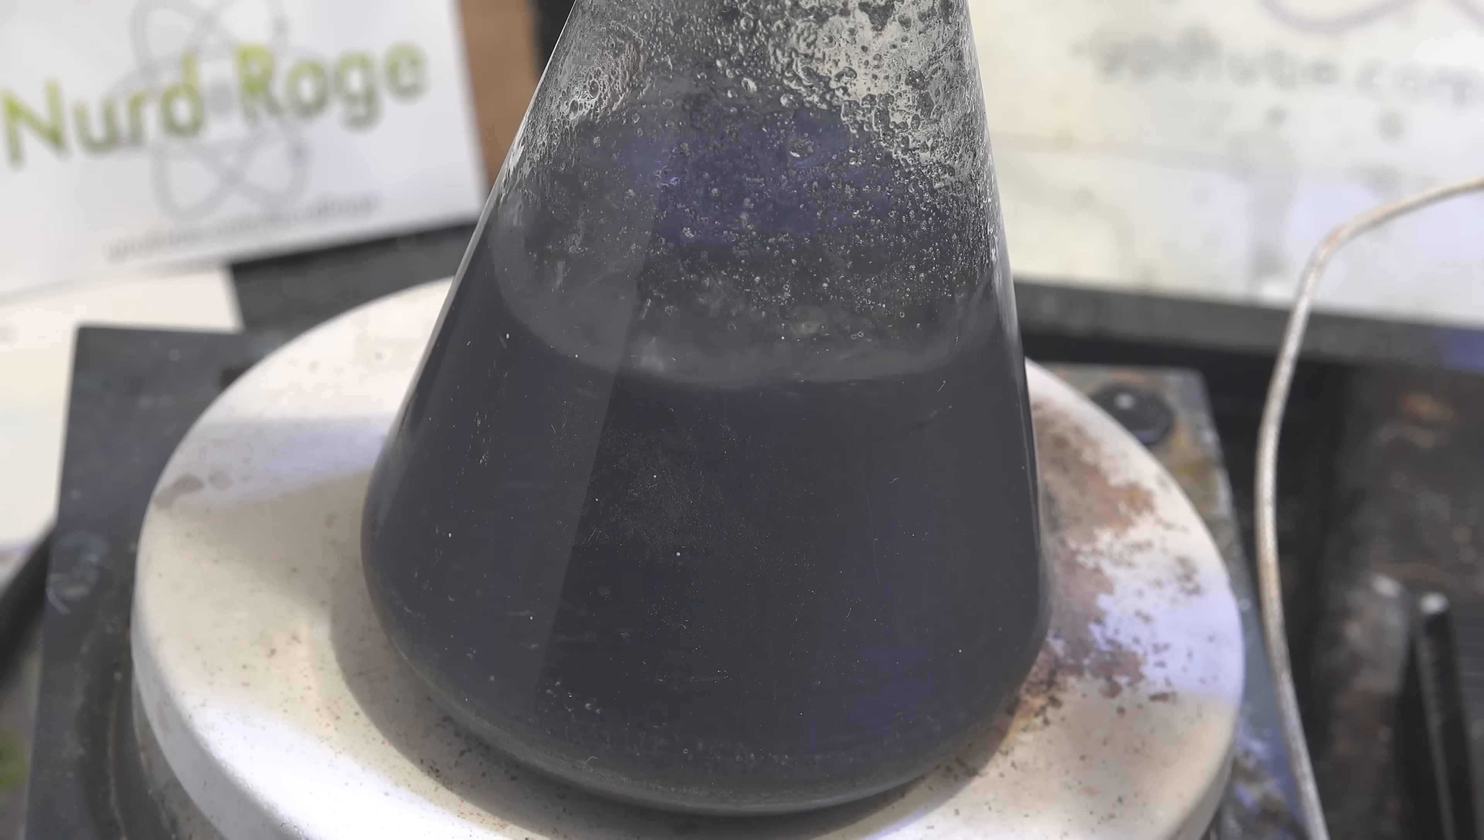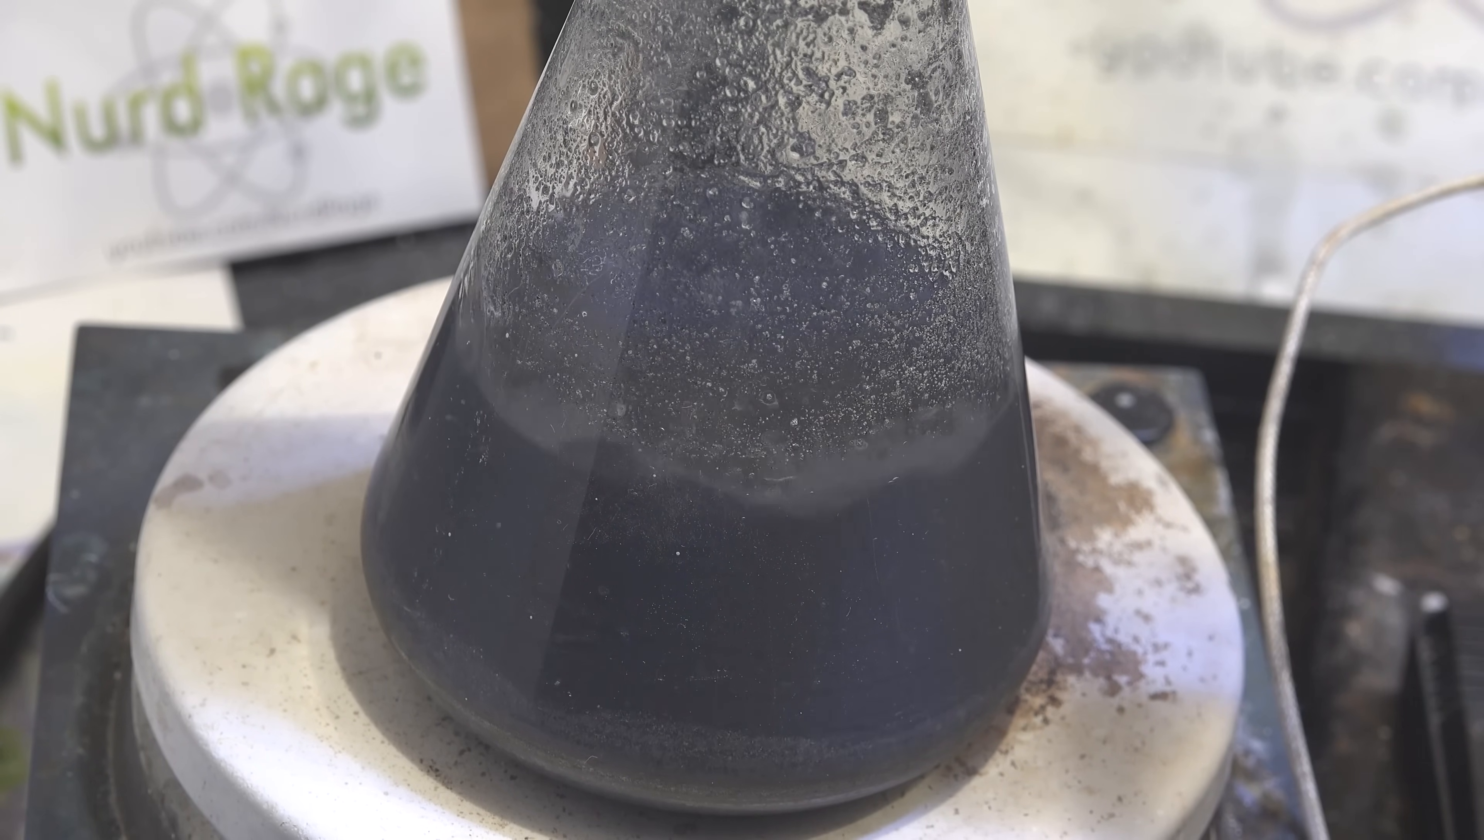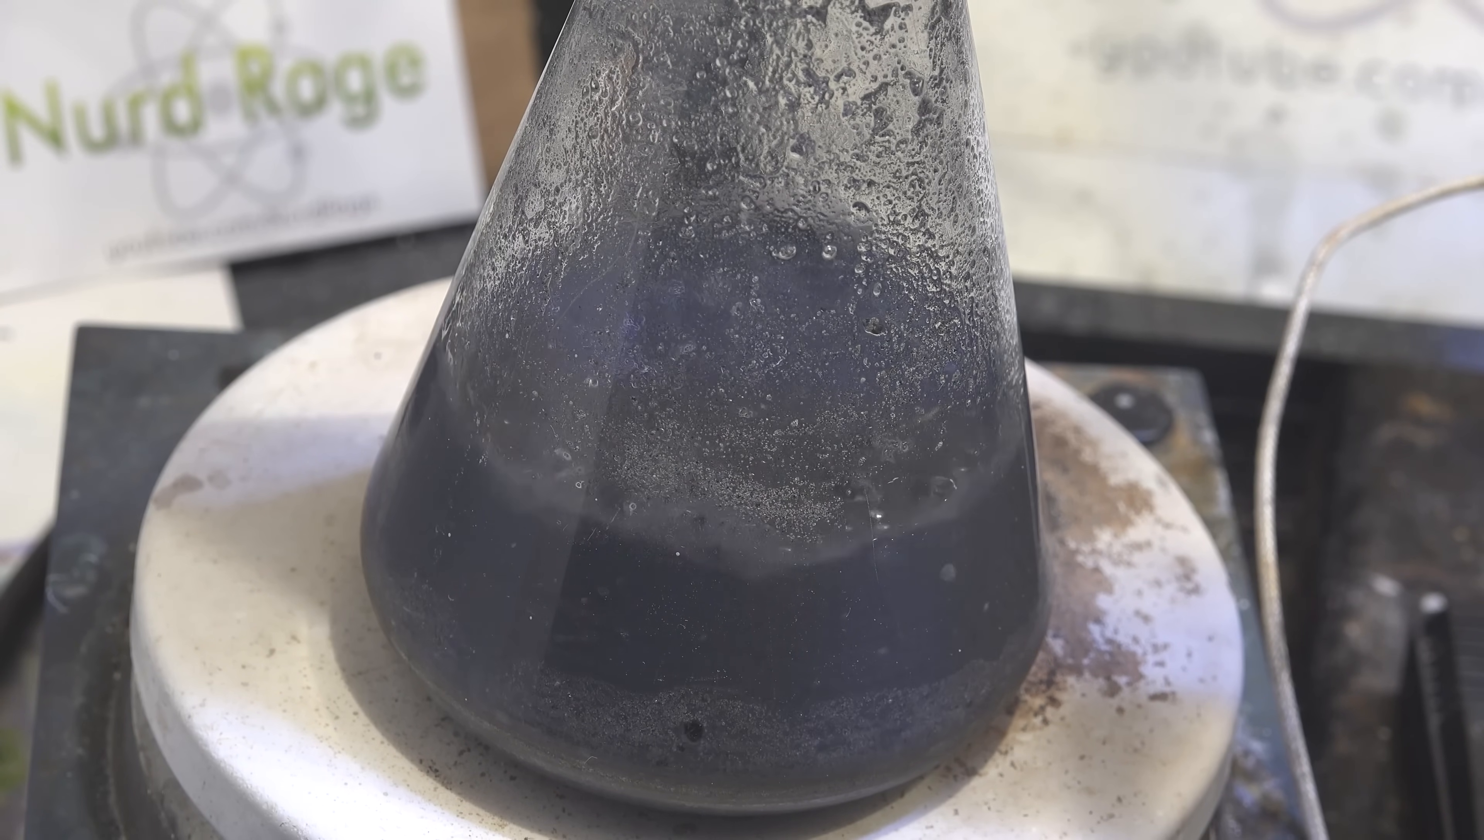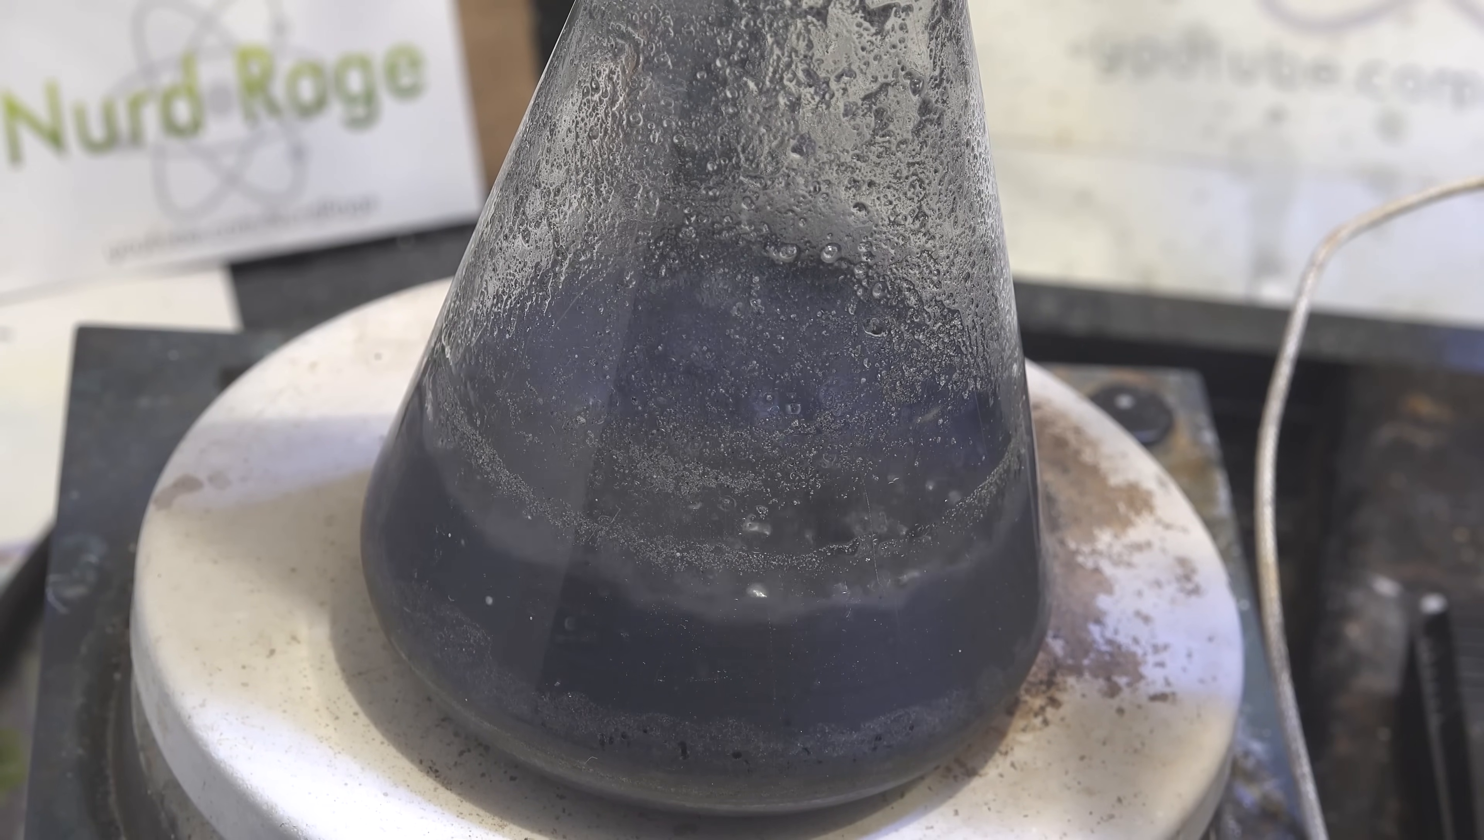Now some people have suggested to distill the sodium out of the aggregate. You can try but considering sodium has a boiling point of 883 degrees Celsius the process is not exactly trivial. You need to make your own steel and copper distillation apparatus and working with those temperatures isn't easy even for a professional lab. The great thing about this dioxane method is that the temperature needed is just 101 degrees Celsius. Which is easy to handle for the amateur with proper ground glass distillation equipment. 101 degrees Celsius is much easier to work with than 883 degrees Celsius.